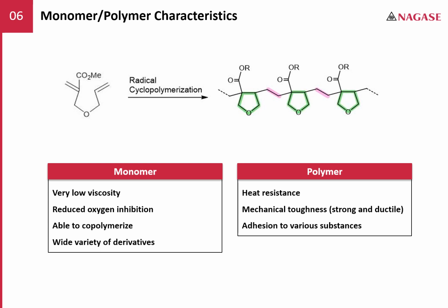Here we see the reaction on the top end of this slide, just similar to what we saw on the previous slide, but cutting out any of the side reactions. So we have your AOMA undergoing a radical cyclopolymerization, and you form this polymer chain that is composed of the tetrahydrofuran structure and the alkyl structure, giving it your rigid and flexible parts.